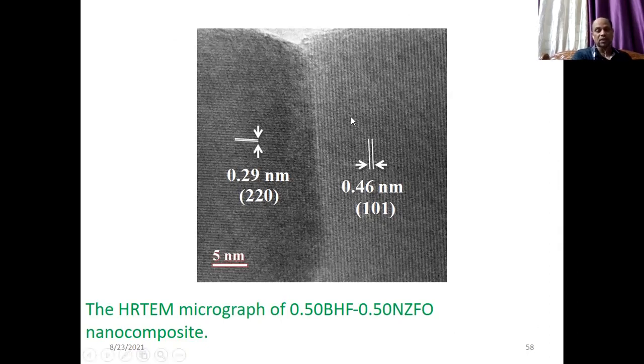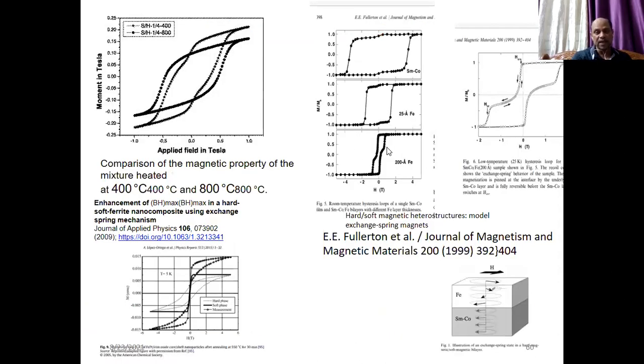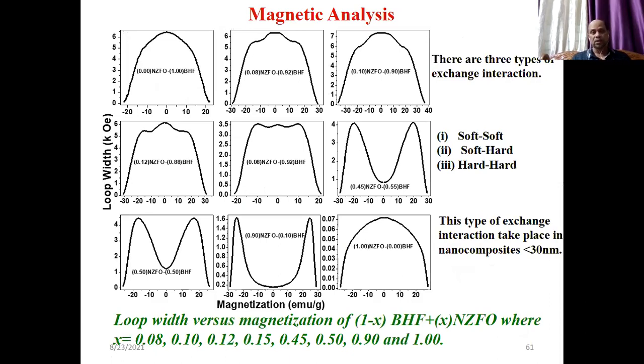But we see that if it is continuous, why should they give this biasing? If you have a spin distribution function continuous, why will they bias each other? Okay, it is a continuous spin function. So by interacting with each other, they will modify each other, and they cannot do it independently; they cannot modify their magnetic moment. That's why there is a lot of research on this, done in different ways, first order reversal curves, etc. It is established, and so many people have done that how the spin structure at the interface is changing its orientation. But what we propose, and this is the interesting thing, is to take loop width versus magnetization.